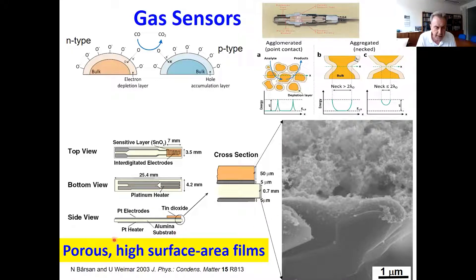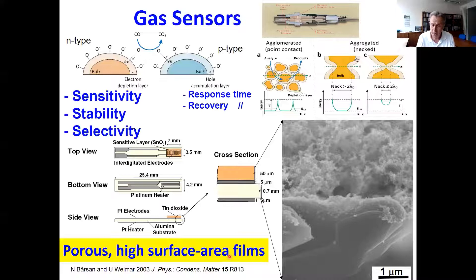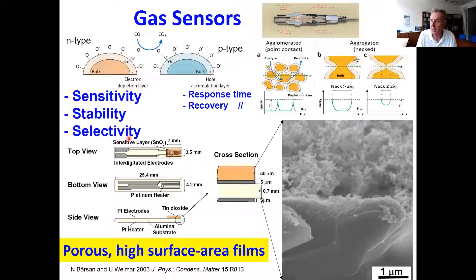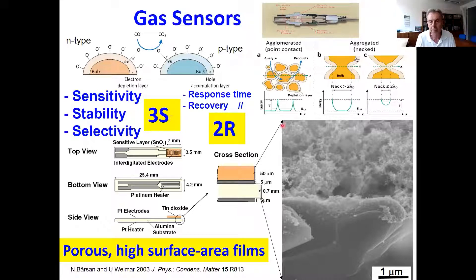We are looking for porous, high-surface-area films. A sensor must have high sensitivity to detect gases like ammonia and acetone, stability to work for many hours, days, months, or ideally years, and — critically — selectivity. With breath containing a thousand compounds, the sensor must be able to pick up acetone unambiguously. It also needs fast response and recovery time. In the field we refer to the three S's and two R's that a sensor must fulfill: sensitivity, stability, selectivity, response, and recovery.